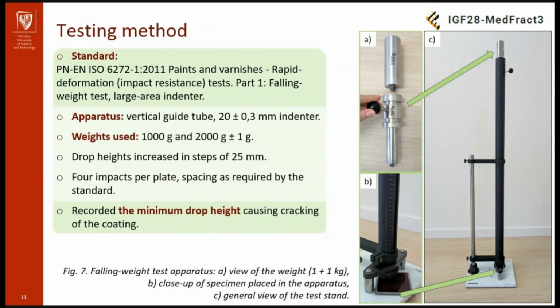I used weights of 1 and 2 kilograms and dropped them from a height increased in steps of 25 millimeters. I recorded the minimum drop height which caused the cracking of the coating.